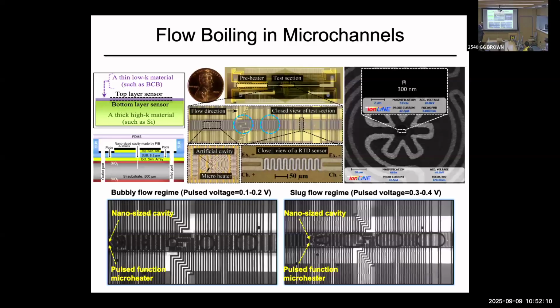There wasn't such a prominent discussion about the implementation in data centers, but my group and some other groups have started working. So what we did, we essentially made a lab on a chip where you could generate bubbles at will from a nucleation site by having a pulse heater. And essentially we have different heat flux sensors, in different directions to measure stuff, and heat flux sensors on the silicon substrate. And this is what it is.